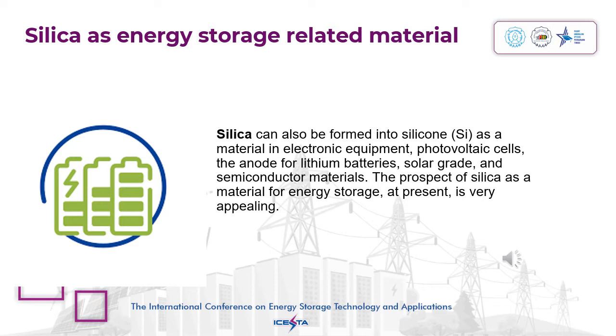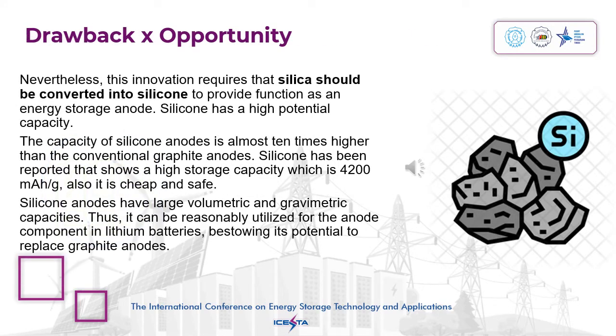The prospect of silica as a material for energy storage at present is very appealing. Nevertheless, this innovation requires that silica be converted into silicon to function as an energy storage anode. Silicon has a high potential capacity. The capacity of silicon anodes is almost 10 times higher than conventional graphite anodes.